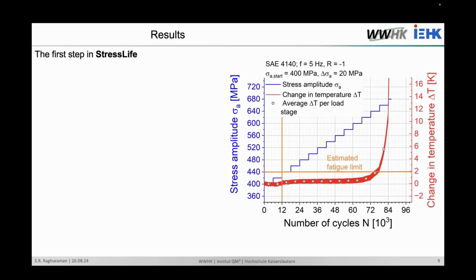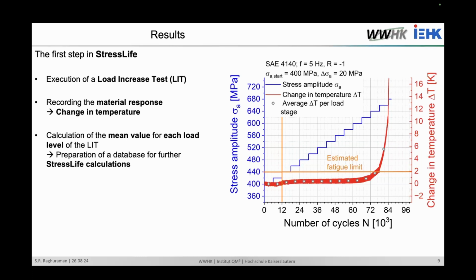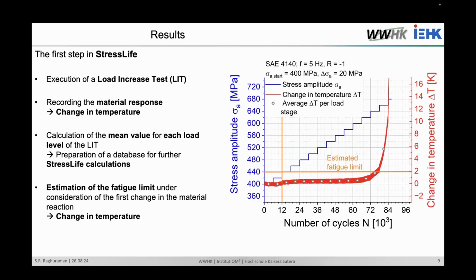So the first step was to conduct a load increase test. Here we have conducted a load increase test starting at 400 megapascals, and we have increased each step by 20 megapascals. The duration of each step is 6,000 cycles. For simplicity's sake, I have just used thermal data for representing the cyclic deformation curves. And here we have a slight increase, the first considerable increase, that we consider as an estimation of the fatigue limit. We have taken the data for each load step, and we'll be using the data in the further coming steps as well.